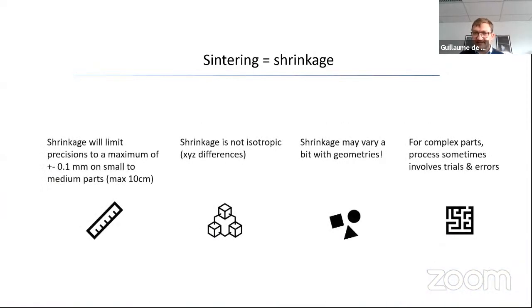If we dive into more detail, the shrinkage will cause some other problems. The first one is it will limit precision to plus or minus 0.1 on a small to medium part, maximum 10 centimeters. And when I say plus or minus 0.1, that's already for someone who really has a good experience of the technology. For some complex parts, it may be more. It is really a limitation to the actual precision of the finished part. If you need more precision than that, that will need some post-machining, almost certainly.